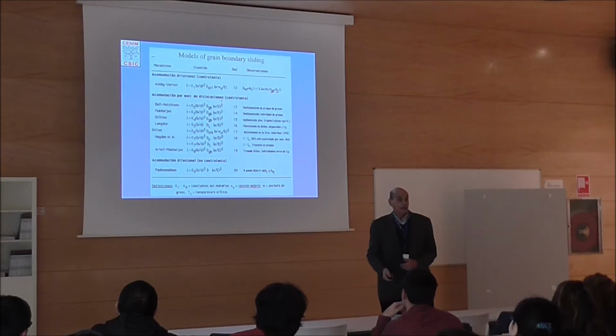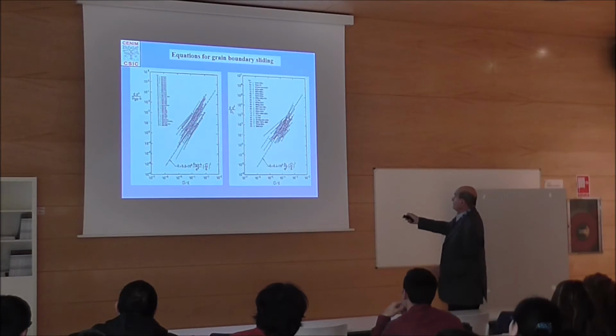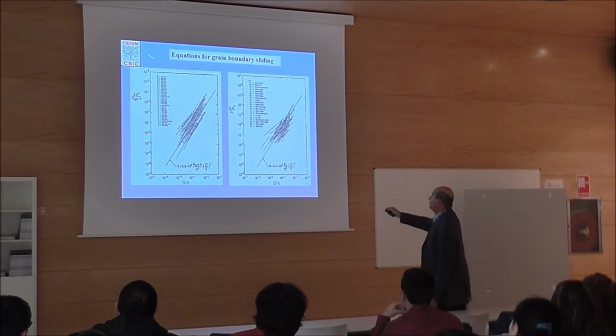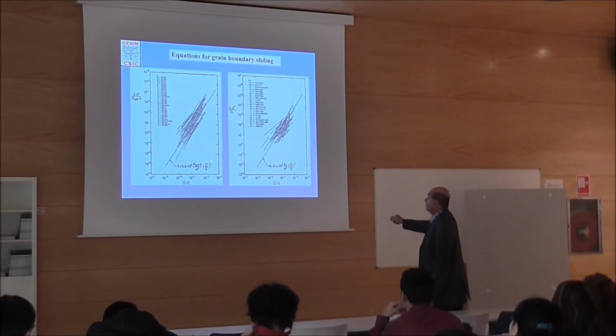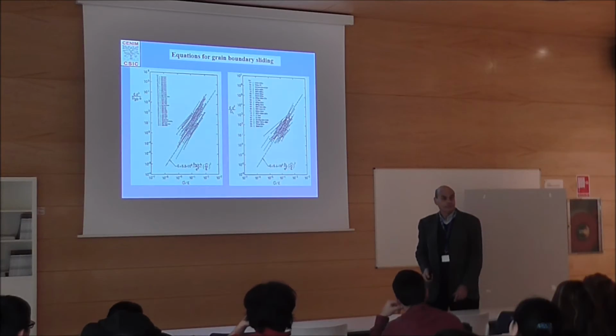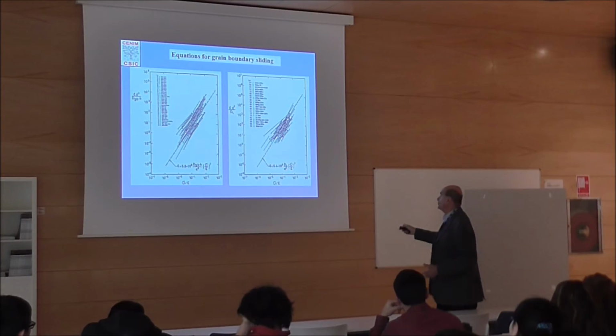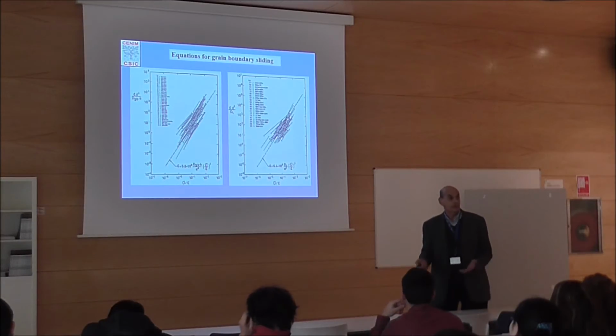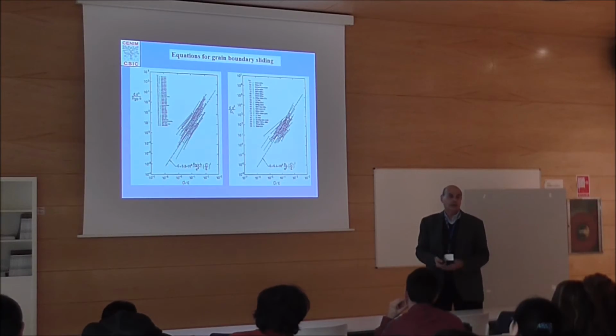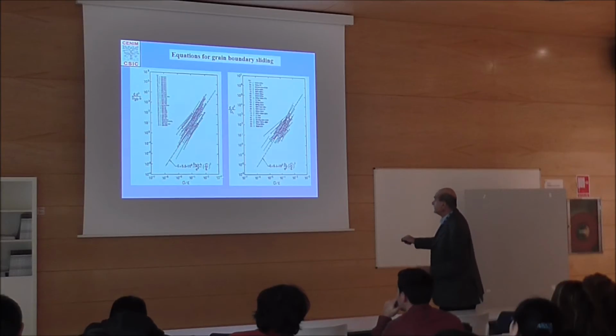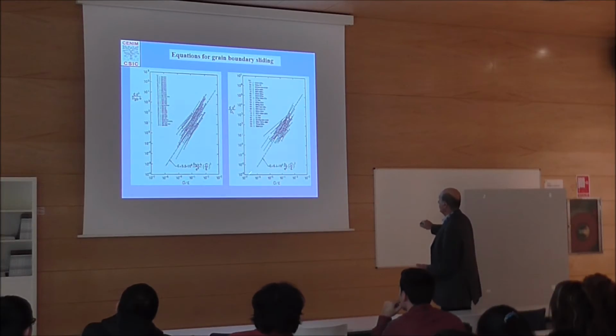So n equal 1, but we have seen that for all these materials, you have n equal 2. This line corresponds to n equal 2. So what's going on there? Why not use this? So what we did is empirical, of course. We took this equation as the reference equation for grain-boundary sliding. This equation goes through the middle of all these n equal 2 materials. And in this case, it was also calculated for n equal 2 materials, one for d squared and one for d cubed, and going to n.